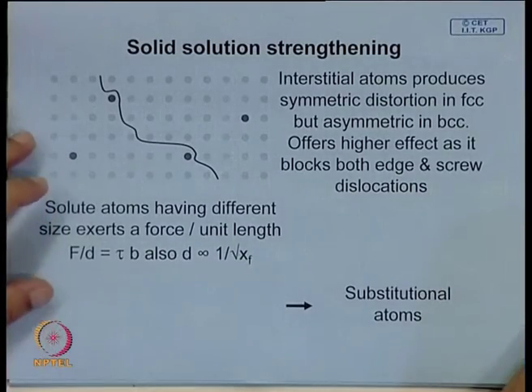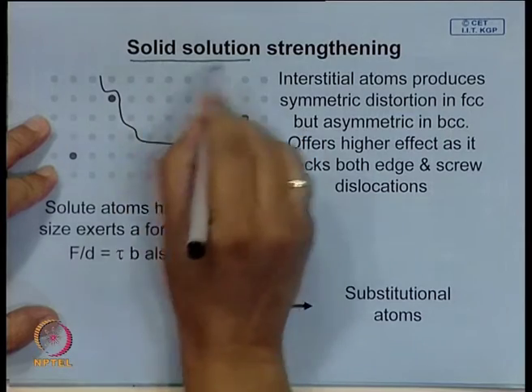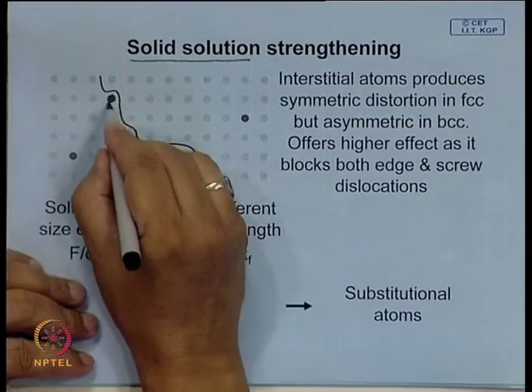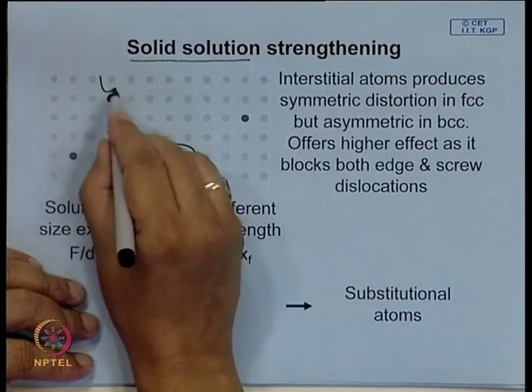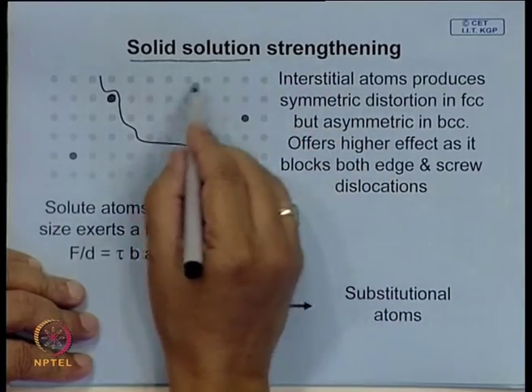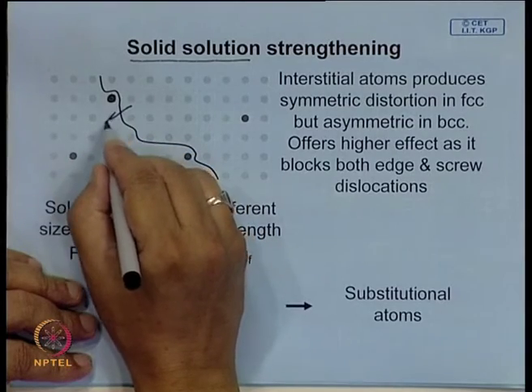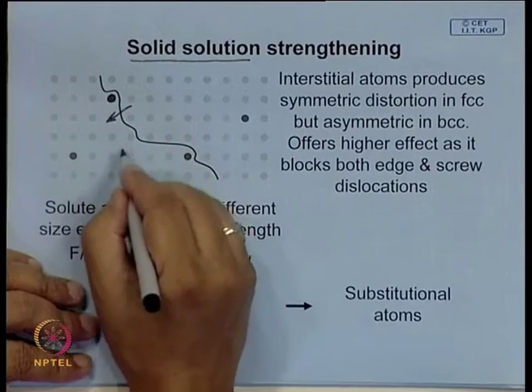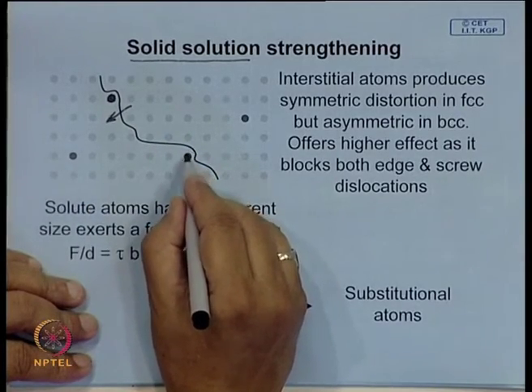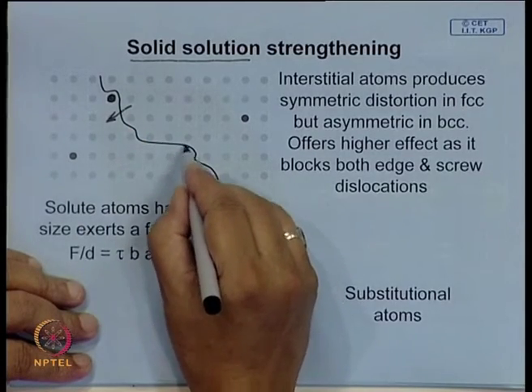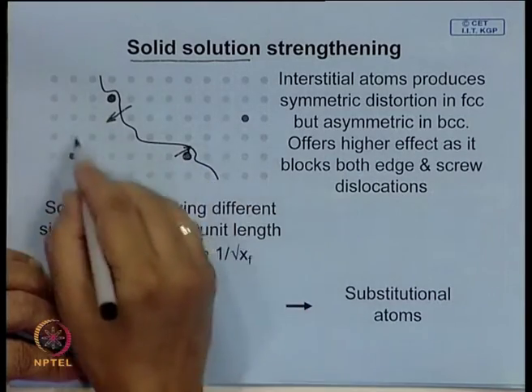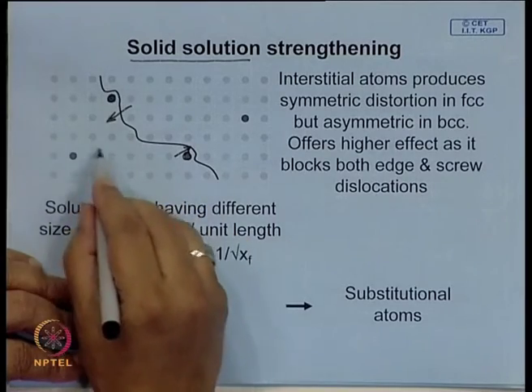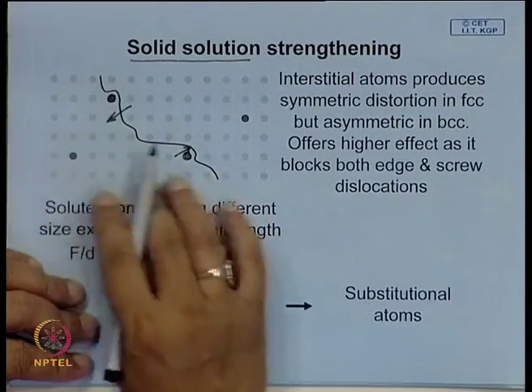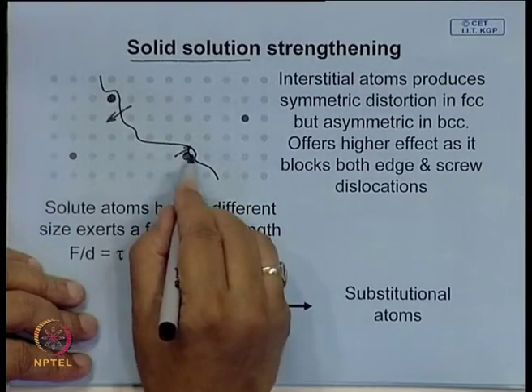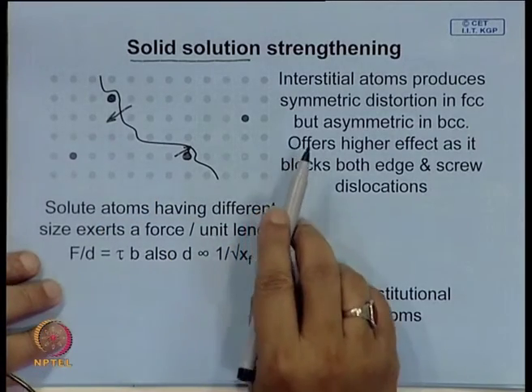Now, a quick look at solid solution strengthening. If you add a solute atom, it will have a different dimension. So, there will be some elastic distortion, it will have a stress field, and we know that deformation takes place through movement of dislocation. Suppose this dislocation is moving in this direction, and this is a stress field. So, it is not free to move. The dislocation movements are hindered by the stress field of these solute atoms, and the overall effect will depend on how closely they are spaced. So, the more the number of atoms, the more will be the strengthening, and it has been possible to work this out, and we will see quickly on this sheet.